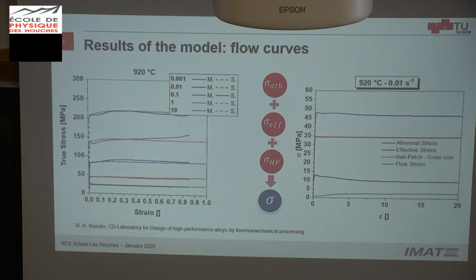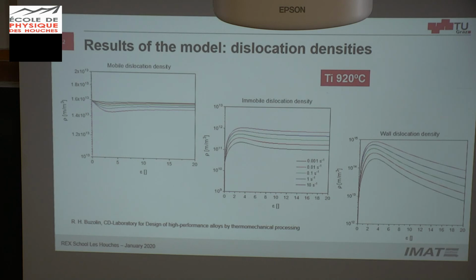Some results. This is only up to small strains. We can catch the softening of the flow at high strains, and we can also catch internal variables: mobile dislocation density as a function of strain, immobile dislocation density, and wall dislocation density, which are decreasing because we have continuous dynamic recrystallization. When the low angle grain boundary becomes a high angle grain boundary, it disappears from here, let's say.